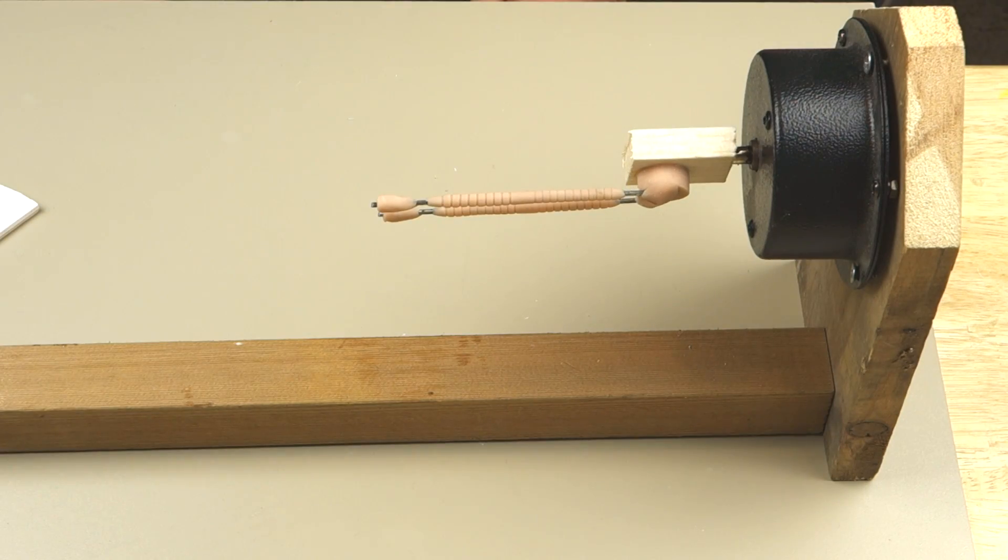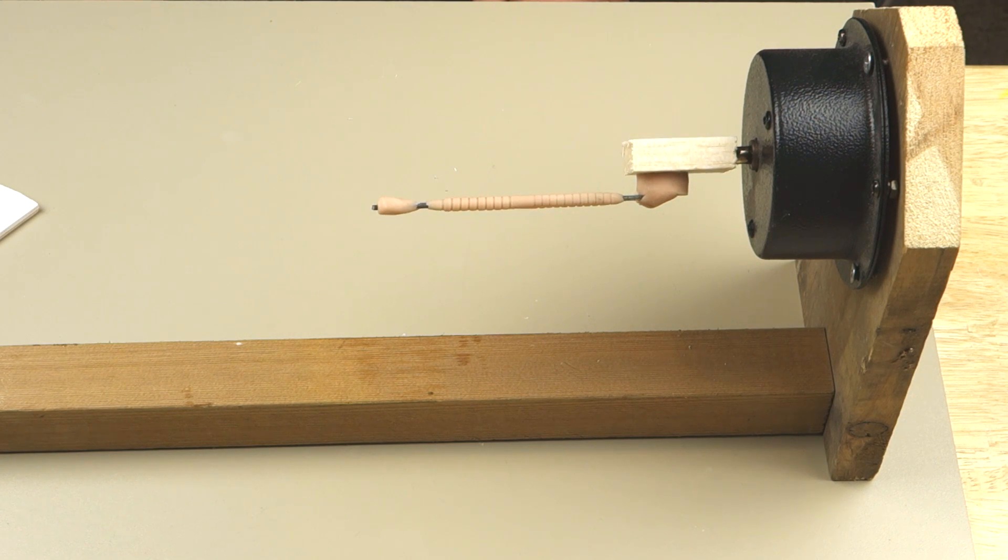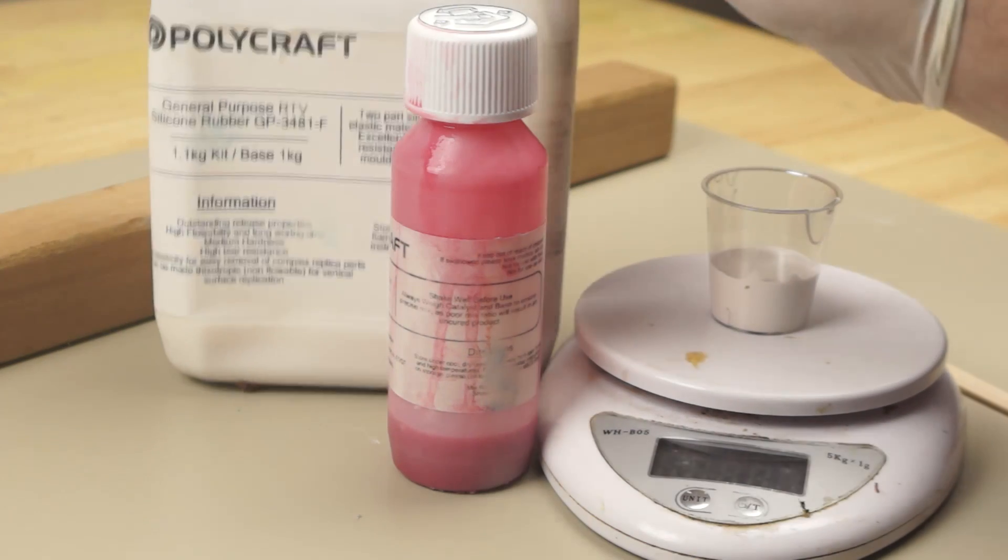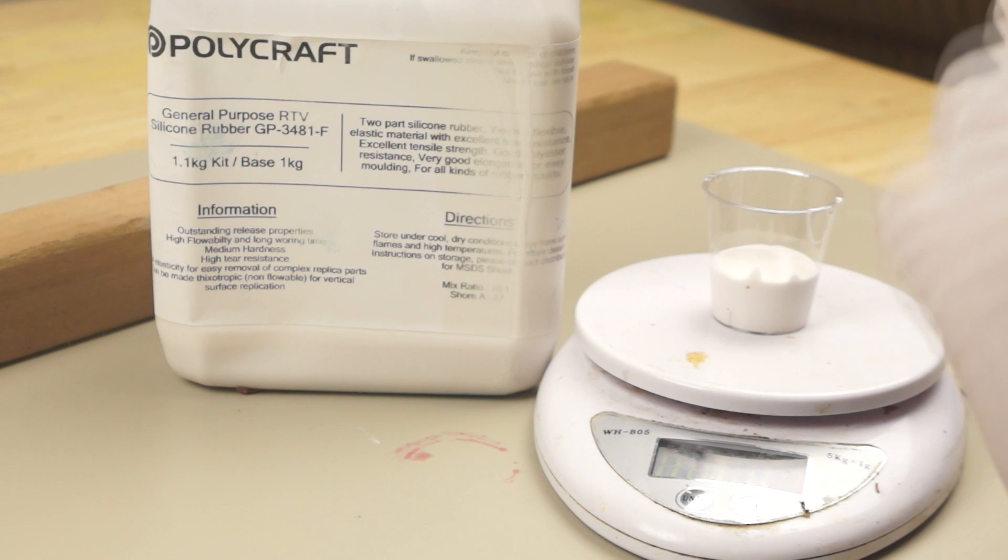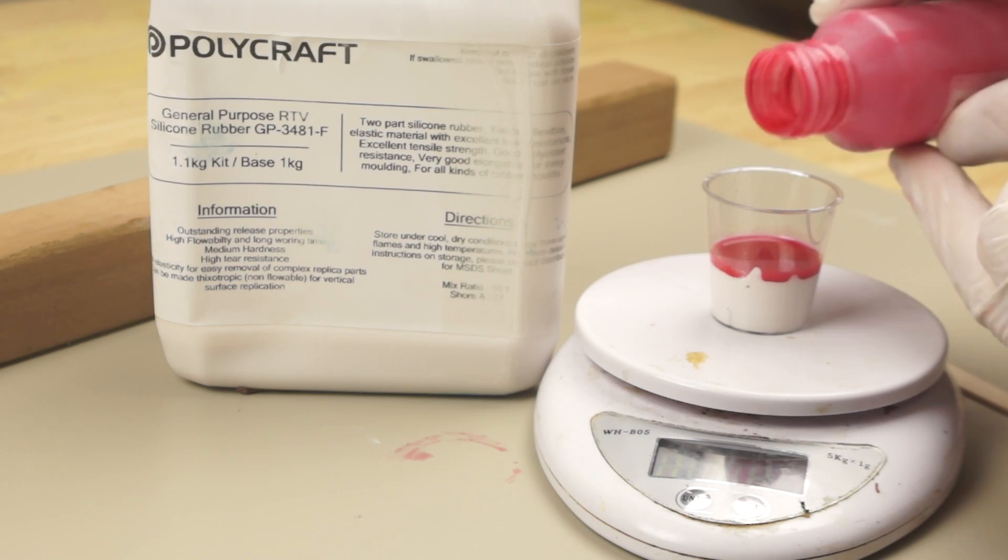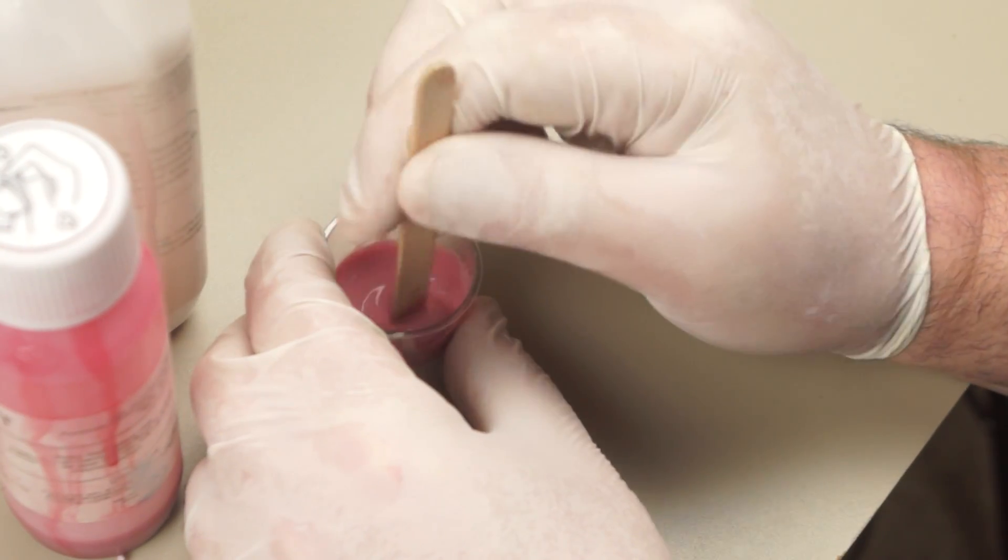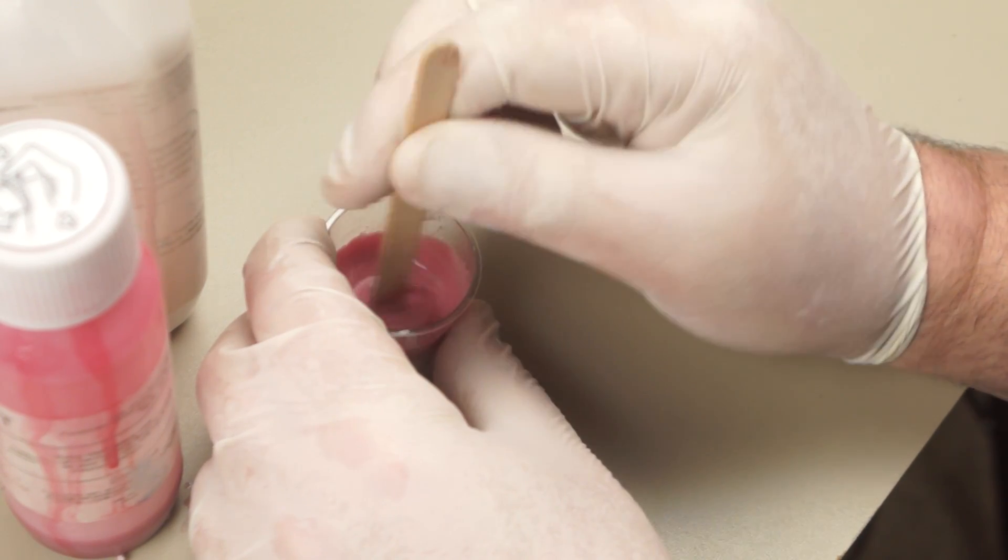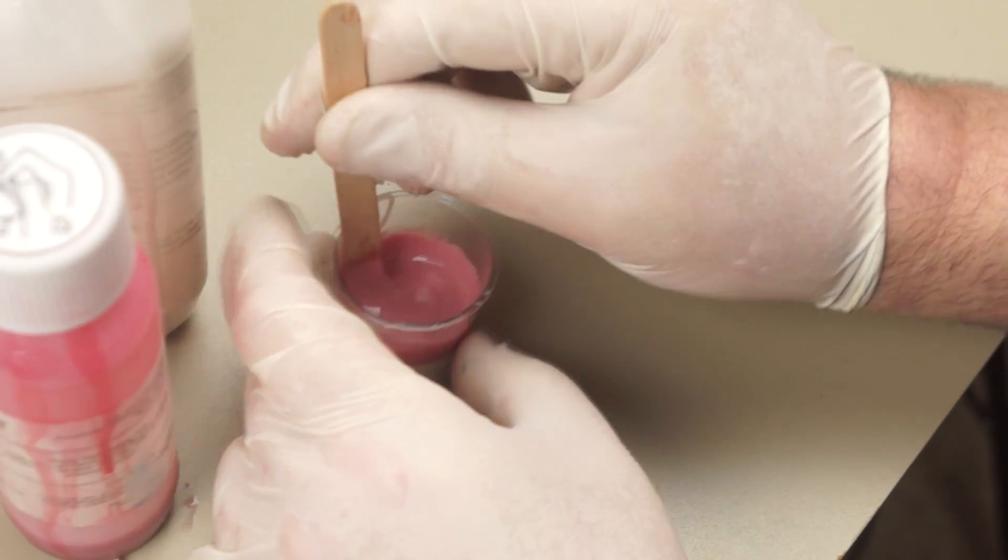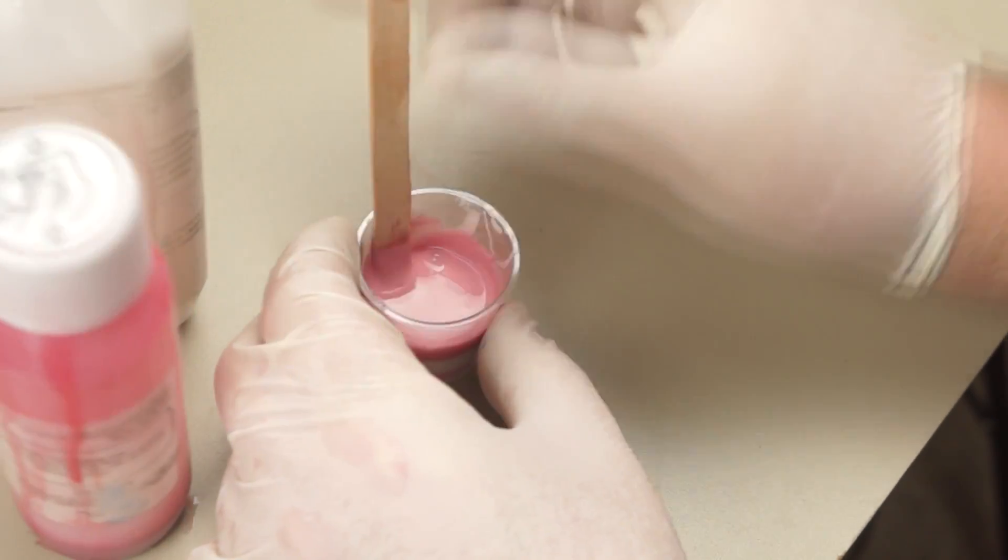I'm going to leave that for a couple of minutes and mix up a small amount of silicone. For the mold, I'm using a two part RTV silicone. I'm mixing up the minimum amount that the scales will measure. This is the catalyst. There's quite a long work time with this silicone. Something like 40 minutes. So I'm mixing it quite slowly because I don't want to include too many bubbles in the mixture. And also, I want to scrape the sides and the bottom.